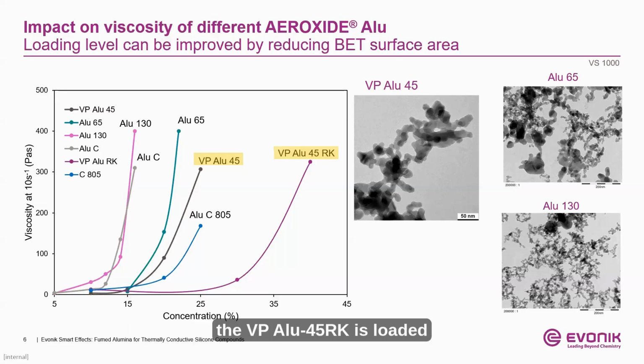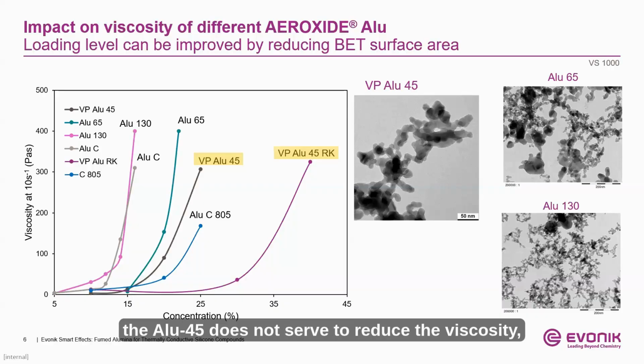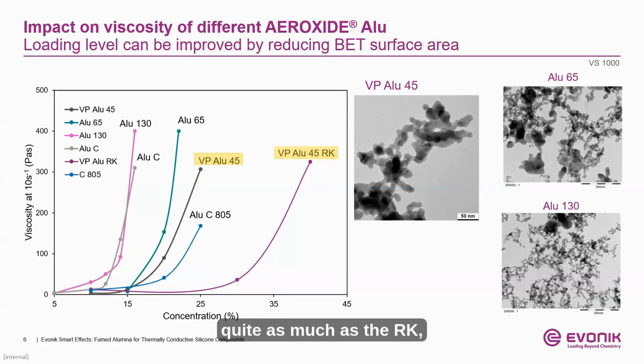As you can see here, the VP Alu 45RK is loaded very highly, as is the 45 itself, the hydrophilic version. You get much higher loading levels with less viscosity impact with both of these materials. As I said, the Alu 45 does not serve to reduce the viscosity quite as much as the RK, which is the hydrophobically treated option. There's a reason for this.